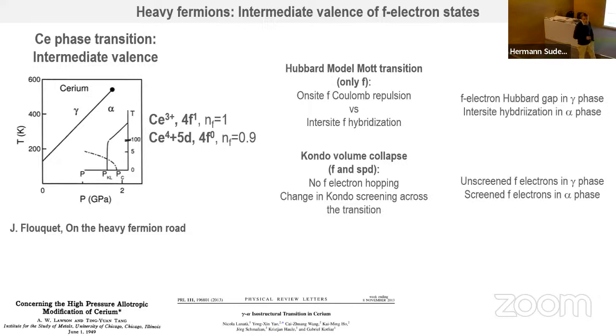So of course, what happens are electron correlations with the F electrons. You switch over from a situation at high temperatures where the F electrons are localized and you have a spin, to a situation where part of the localized F electrons go over to the free electron path, and therefore hybridize with the D electrons. And therefore you lose magnetism at low temperatures, and you have a bit more hybridization.